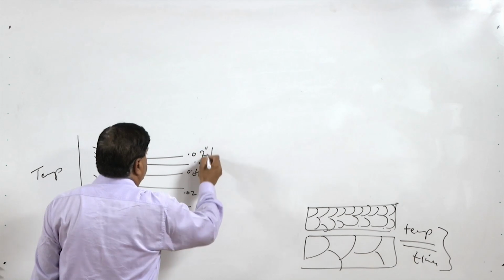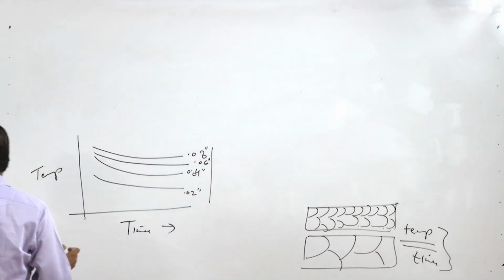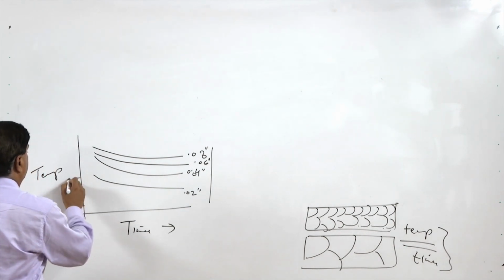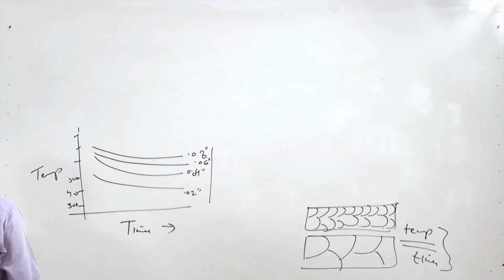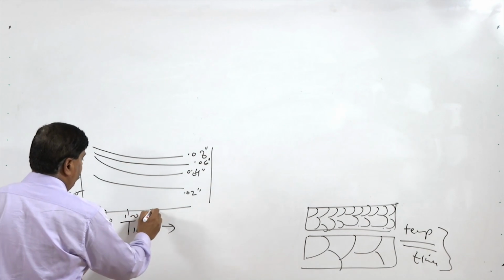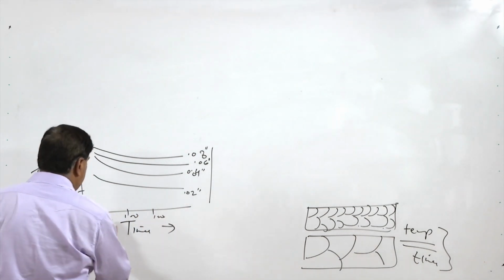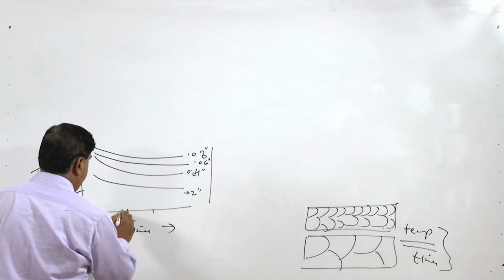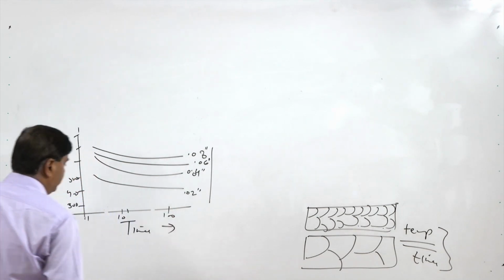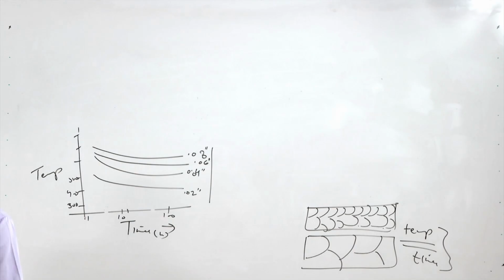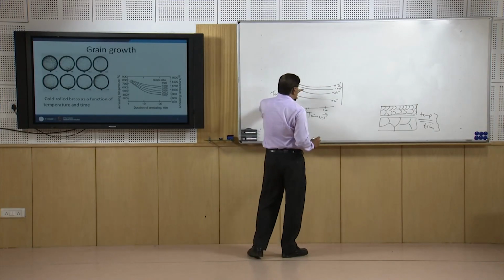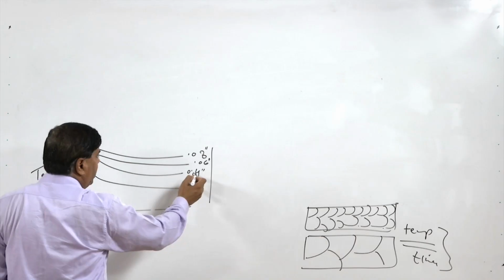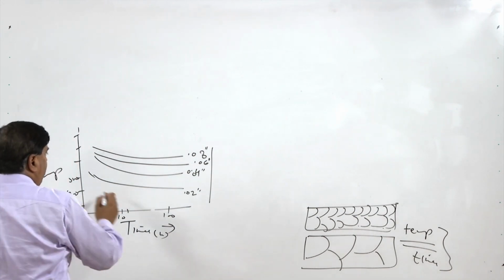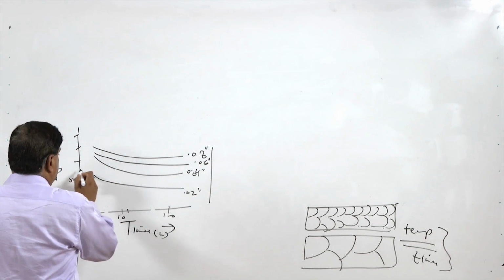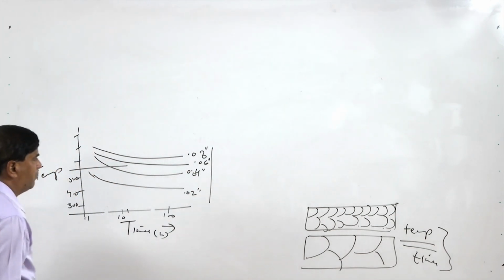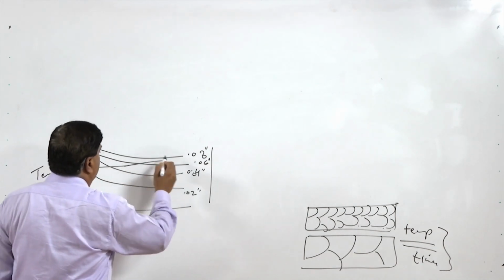0.06. This is the grain size in inches, and typically the temperature values are 300, 400, 500 likewise, and the time is in log scale: 1, 10, 100, 1000, like this. So, here it will be further longer, like say 10 and 100 in hours. So, what we can see here is, for a given grain size, let us say 0.04 inch, how the grain size changes as a function of the time.